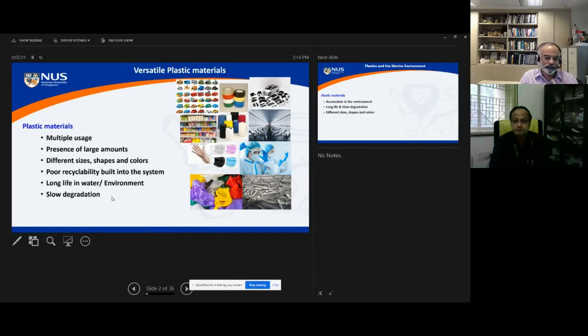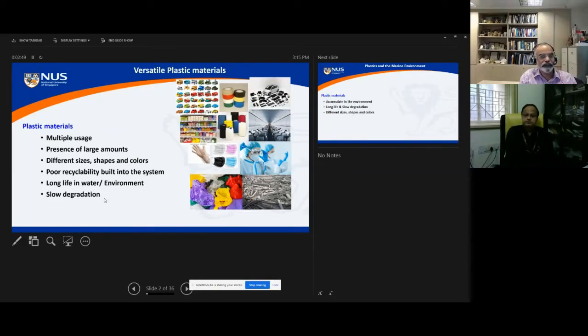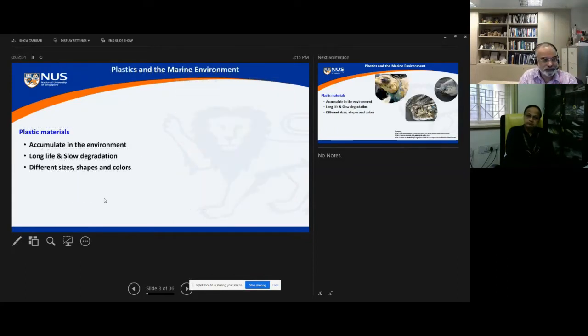The other drawback is that when polymers are produced in a pure form, they are not very stable. They can be degraded very fast. So what the industry does is add all kinds of stabilizers, coloring agents, and plasticizers. Many additives go into this pure polymer, and that improves the life of the polymer a lot. Those additives can also play a huge role in the toxicity of the so-called polymer we talk about. And they degrade slowly because of all these additives being present. It is kind of difficult to handle at this stage.